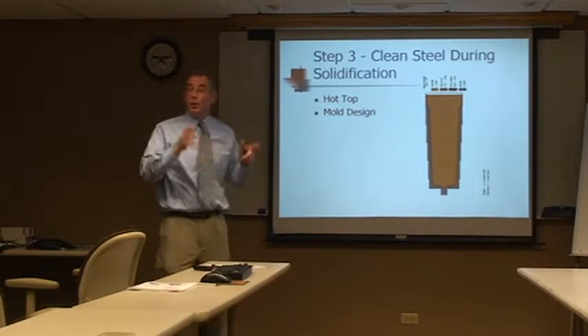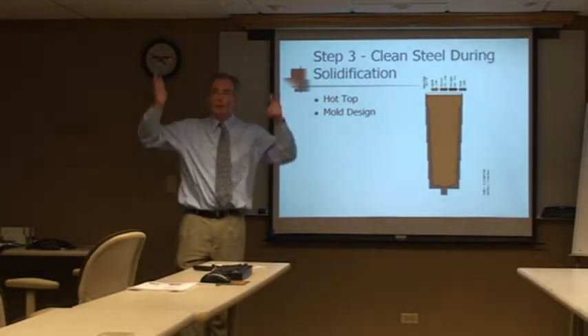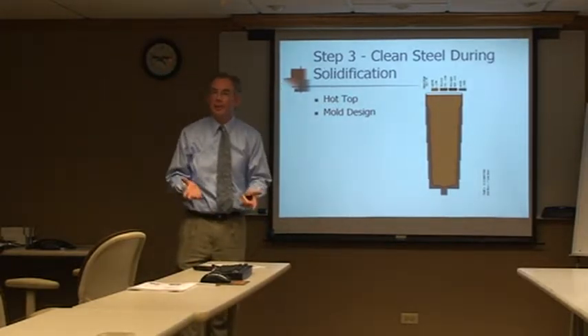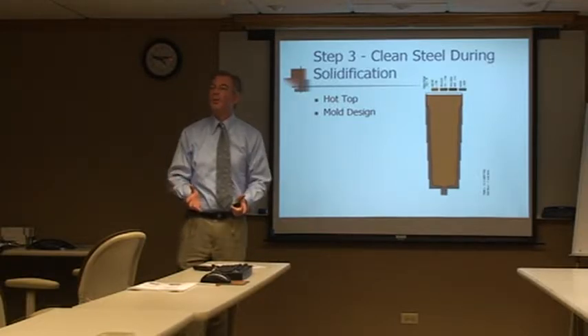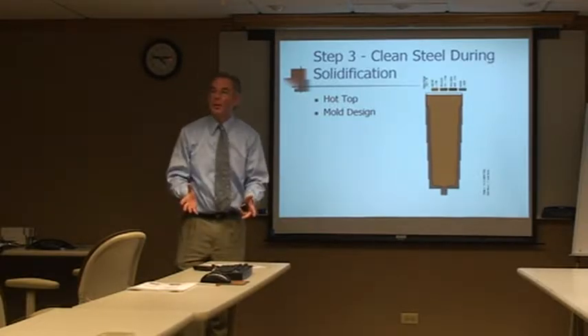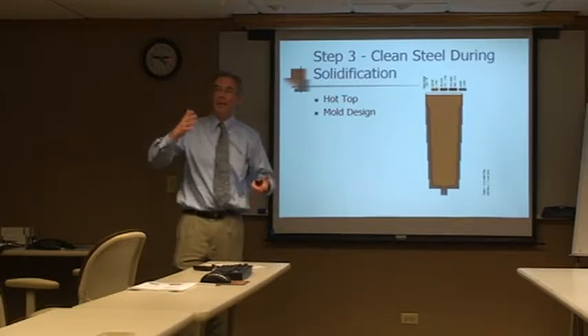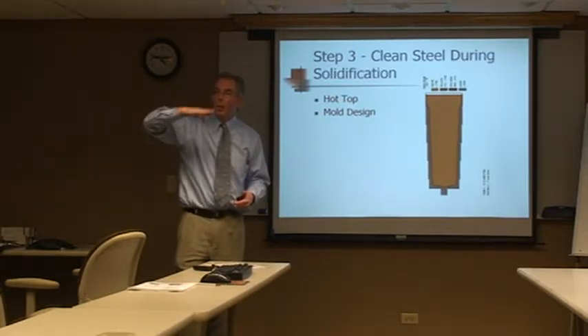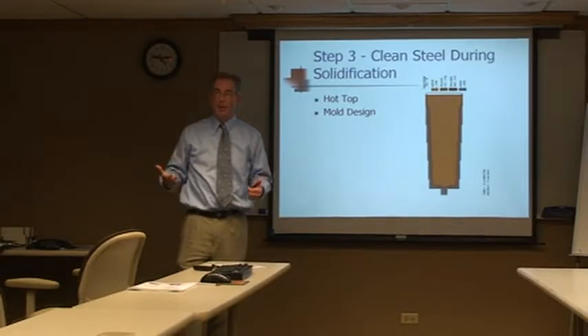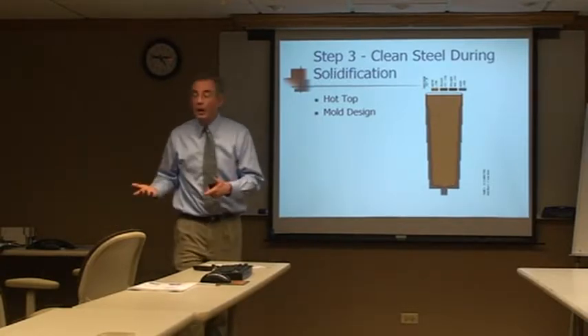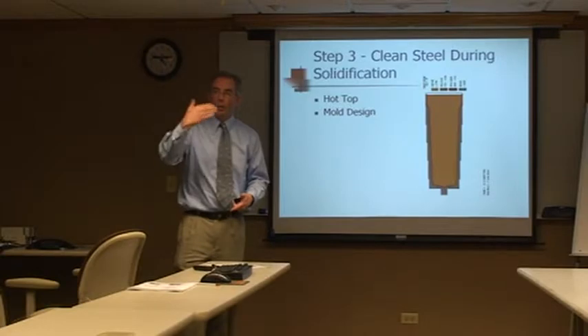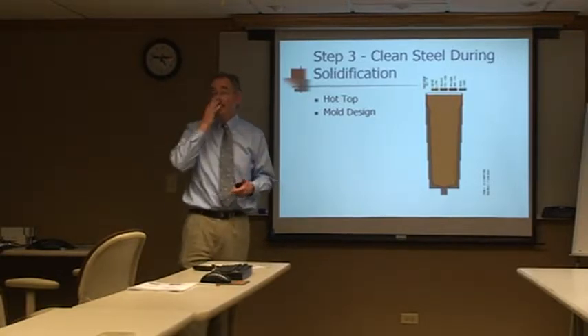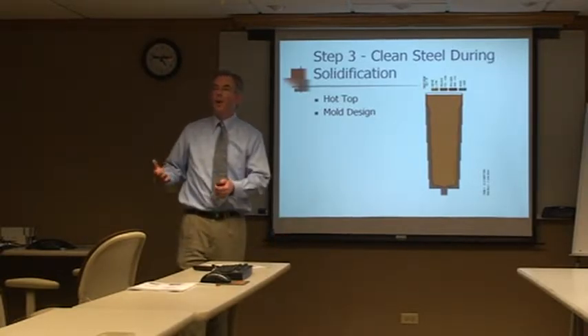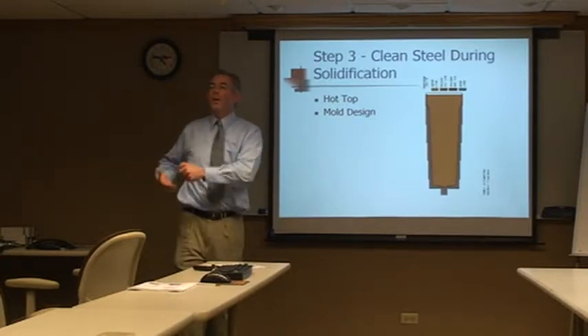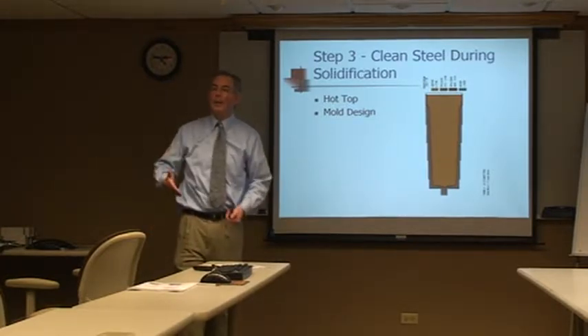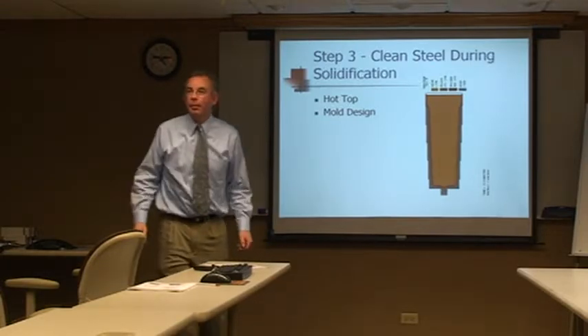Now, when we pour, initially we pour wide open. First 2 minutes, 3 minutes, it's poured wide open. We have to fill the system, otherwise the steel will just freeze off immediately. So we pour wide open, 3 minutes, then we cut back, and then within 3 minutes, we need to be into our steady state teeming, maximum teeming, whether it's 1.0, 1.1, 1.3, and we're recording that as such. If we violate it, it ends up being a non-conformance, or worse, ends up being a cracked ingot or becoming a problem.